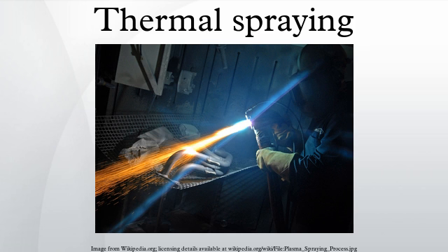The volatile plasma byproducts are evacuated from the chamber by the vacuum pump, and if necessary can be neutralized in an exhaust scrubber. In contrast to molecular chemistry, plasmas employ molecular, atomic, metastable and free radical species for chemical effects, and positive ions and electrons for kinetic effects. Plasma also generates electromagnetic radiation in the form of vacuum UV photons to penetrate bulk polymers to a depth of about 10 micrometers. This can cause chain scissions and cross-linking. Plasmas affect materials at an atomic level.